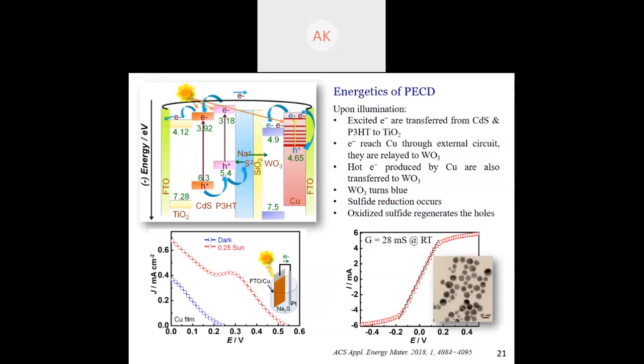So what is the energetics of this PECD? Upon illumination, excited electrons are transferred from CdS and P3HT to the TiO2. Now, electrons reach the copper through the external circuit, and then they are relayed to the WO3. Hot electrons produced by copper are also transferred to WO3. WO3 turns blue. Sulfide reduction occurs and oxidized sulfur regenerates the hole.